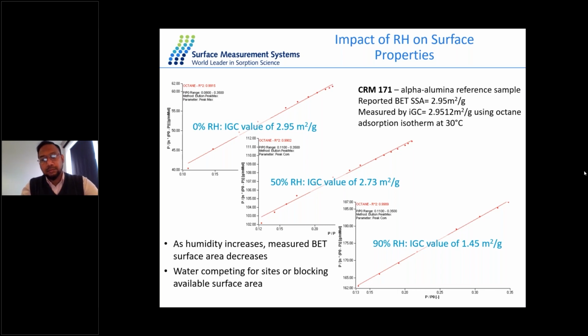One thing to also understand is that it's very good at comparing the dispersive interactions between your materials, so the dispersive surface energy, because you're using a set of non-polar probe molecules. However, if you're looking at the specific surface energy, what you're looking at is the polar probes, and the specific surface energy is directly related to the interaction of these polar probes. So to compare the two techniques, you would want to have the same polar probes for each experiment to be able to have a direct comparison.